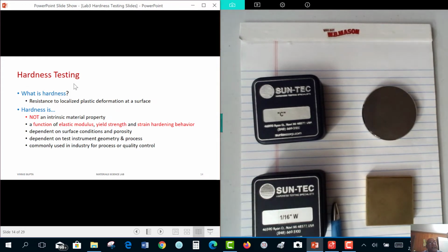Okay, so let's talk about hardness testing. What is hardness? Hardness, as you know, is resistance to localized plastic deformation at the surface. So this is what we meant by indentation hardness. When we did Brinell hardness testing, we applied a force on the indenter and caused that indent. Now it turns out hardness is not an intrinsic material property. You saw that it does not appear anywhere on our tensile testing curve. In fact, it is a function of 3 of those tensile testing properties: elastic modulus, yield strength, and what we call strain hardening behavior. Quantitatively, we characterize that as the strength ratio of tensile strength to yield strength. So we are going to talk about this a little more in a minute.